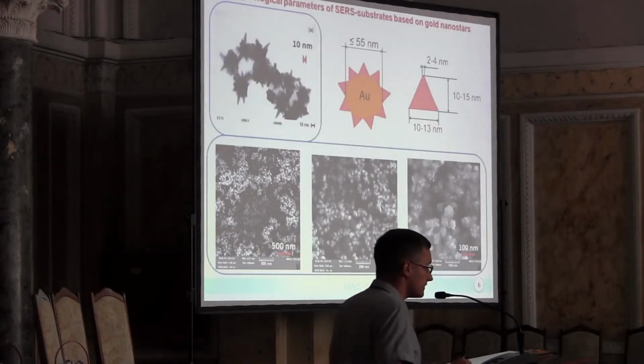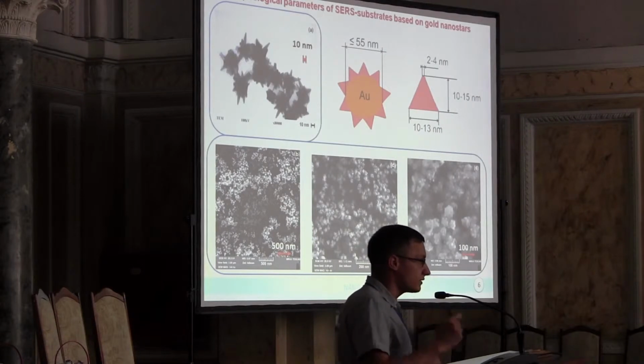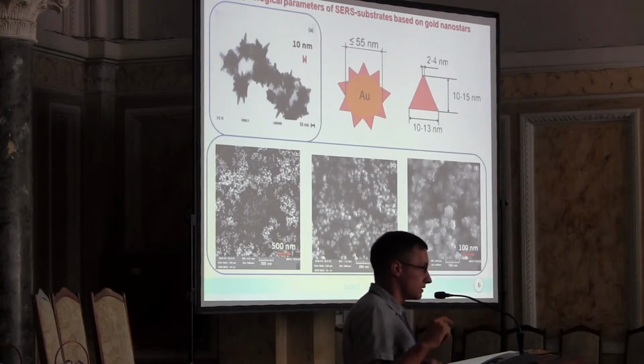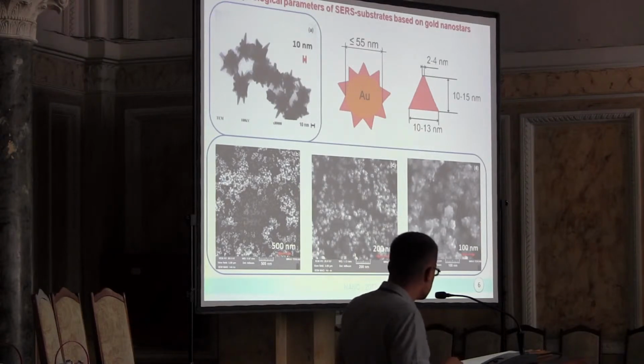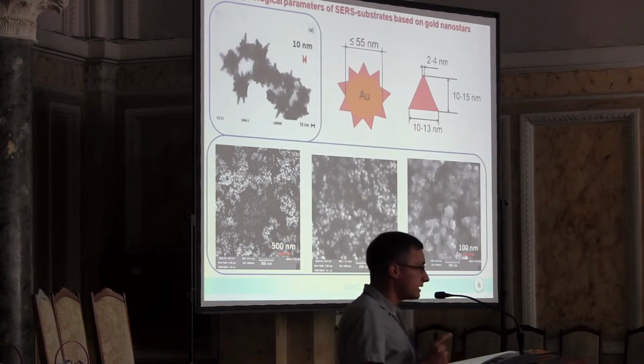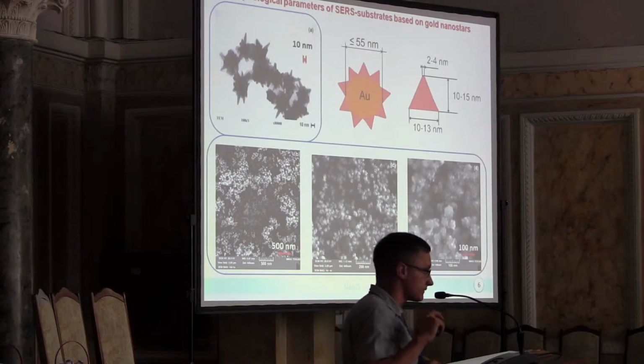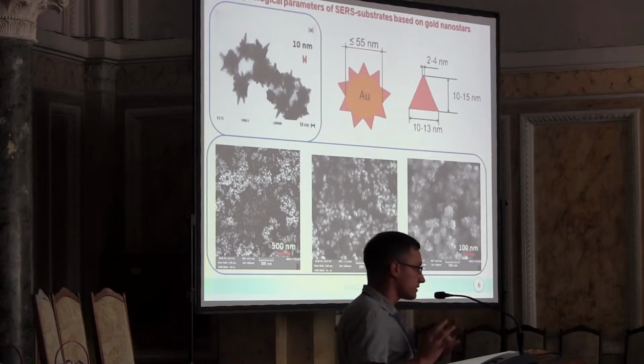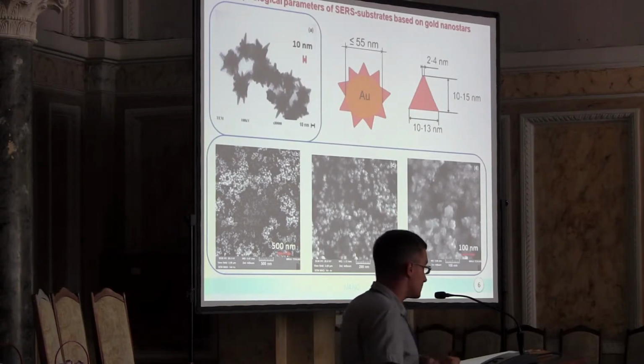In this work we have synthesized by colloidal method gold nanoparticles in the form of stars, as you see on this slide, and the main feature of these nanoparticles is that they have a lot of edges on their surface where a high electromagnetic field could be localized.